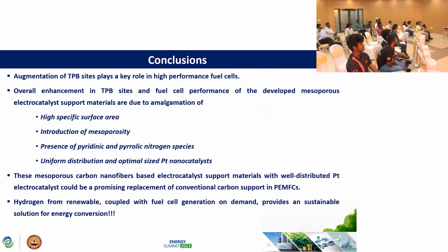To conclude, we understand that instead of just increasing the surface area, we should focus on improving the triple phase boundary sites, which should play a major role in improving the performance of PEM fuel cells. In the case of the mesoporous carbon nanofibers, the overall enhancement in triple phase boundaries was achieved through a combination of characteristics like high specific surface area, introduction of mesoporosity, and the presence of nitrogen-doped sites like pyridinic, pyrrolic, and graphitic nitrogen species. All these characteristics have aided in uniform distribution and optimal size of platinum nanocatalysts over the surface of mesoporous carbon nanofibers.